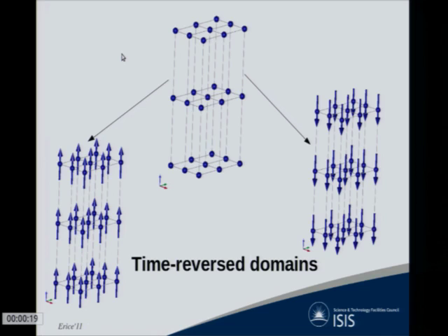So, but there is one important symmetry operation that you have lost. It's time reversal symmetry. This is usually a symmetry that, if you are a chemist and you're doing structural work, you will usually not consider at all because it's actually irrelevant for polar vectors. But here, this is not irrelevant. So if you cool a system that becomes ferromagnetic, you have two possible ground states, in this case of a very simple Ising magnet, that will be related by the moment pointing up or pointing down. And these two things are in themselves a spontaneous symmetry breaking of time reversal symmetry.